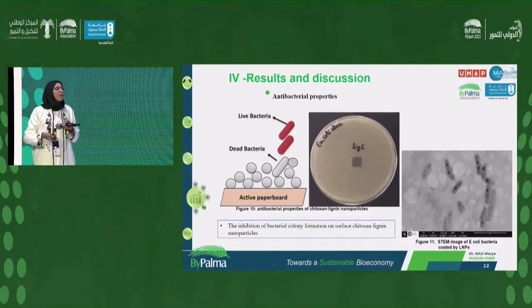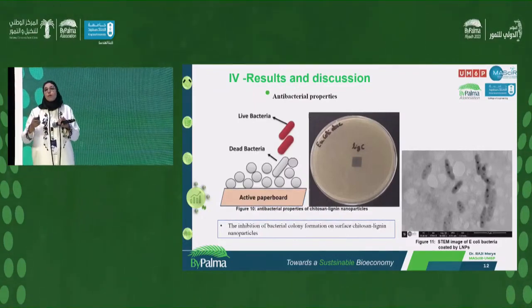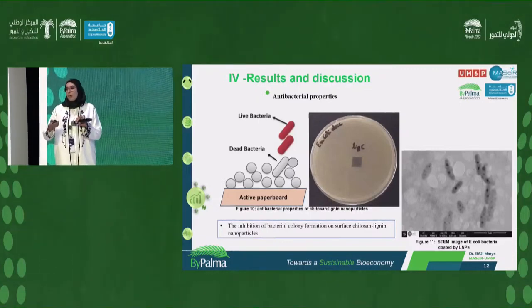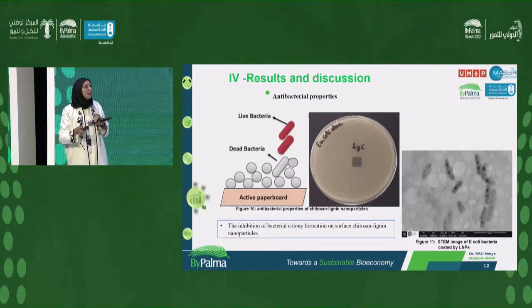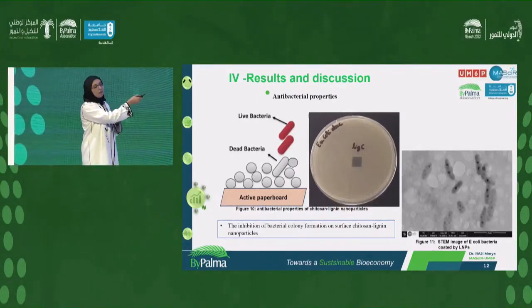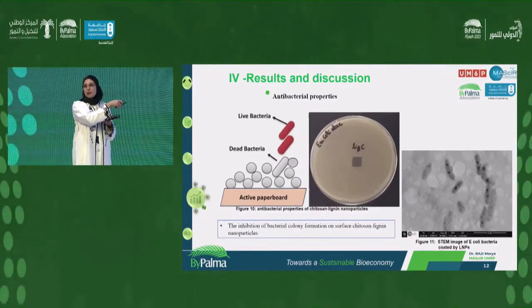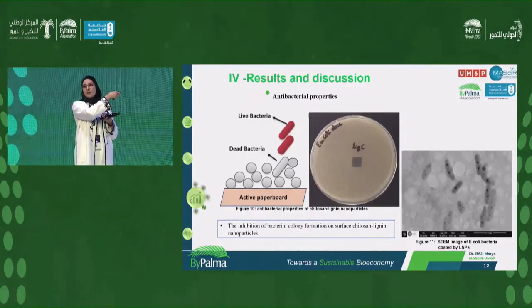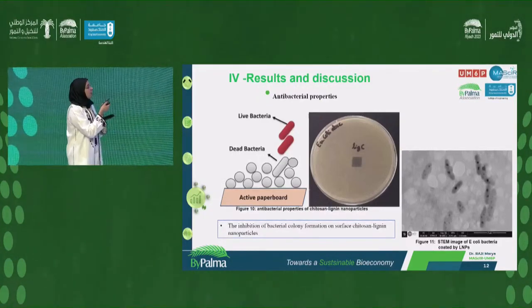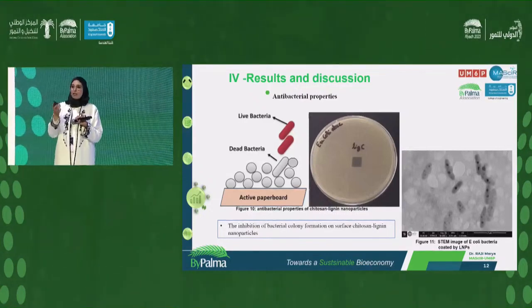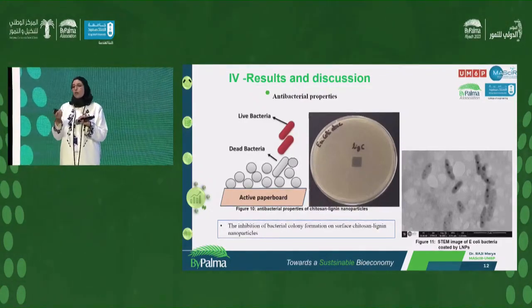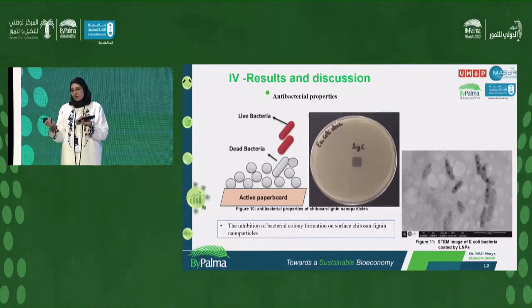So here we can talk about antimicrobial properties of lignin, and many researchers talk about the antimicrobial properties of lignin. The reality is, as we see here, that we have bacteria coated by the lignin nanoparticles, which confirms the antibacterial properties by this transparent area under the film. Here we can conclude that we have an adsorption or coating of the microbes by the lignin nanoparticles, and the inhibition of the bacteria, which is good for our food to improve the shelf life and the quality of our food.